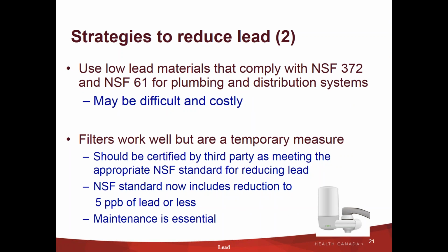Other things that we've recognized in terms of strategies for reducing lead is sometimes you may have to go to things like low lead materials, when it can be costly and difficult. So it's not our first go-to, but it's part of the strategy going forward, things that they can look at to see what they can do to reduce the exposure to lead. And we've recognized that filters work well. They are a temporary measure, and they need to be certified by a third party as meeting the appropriate standard for reducing lead under the NSF set of standards as well.